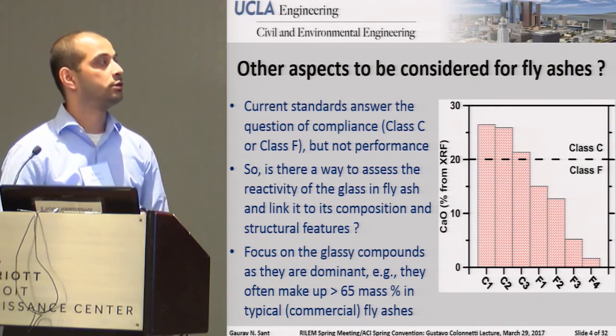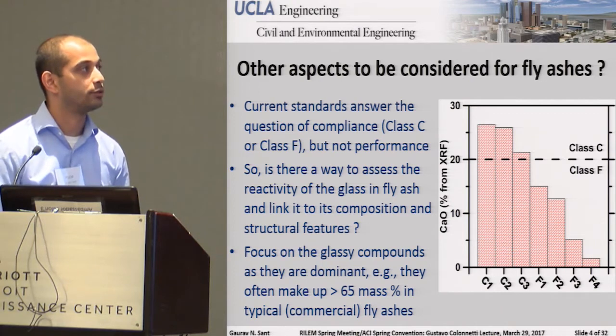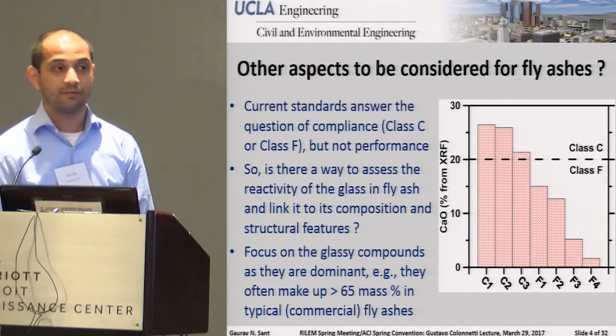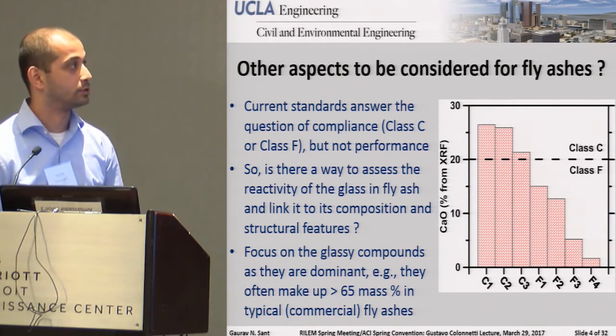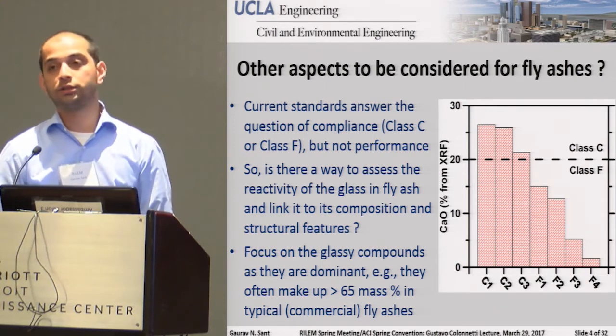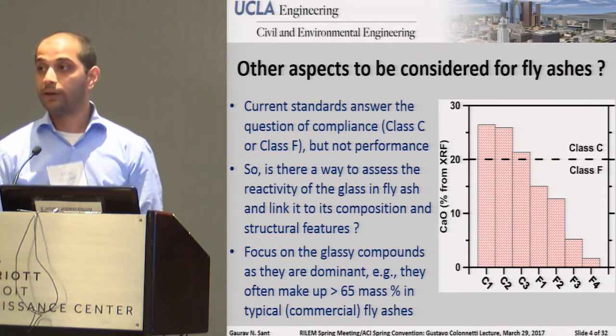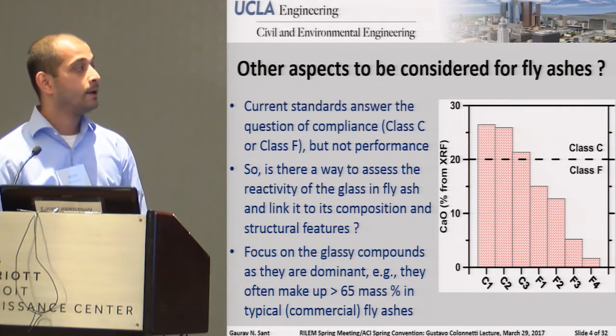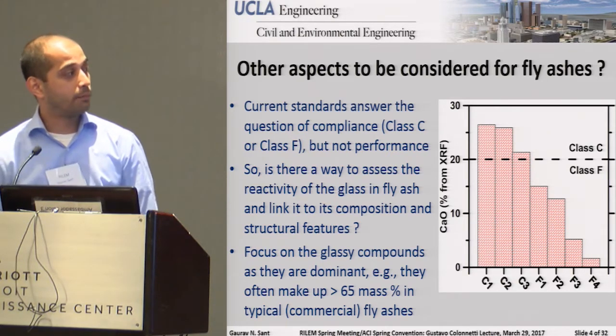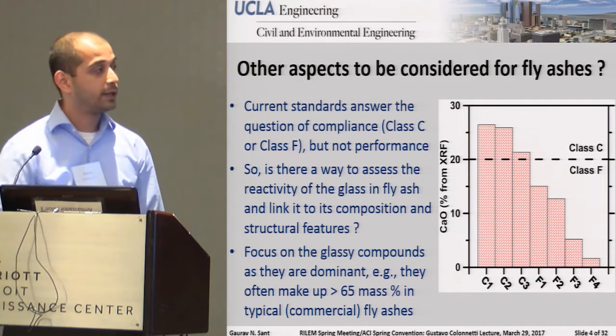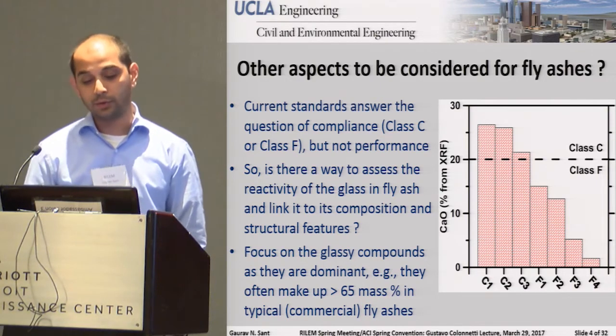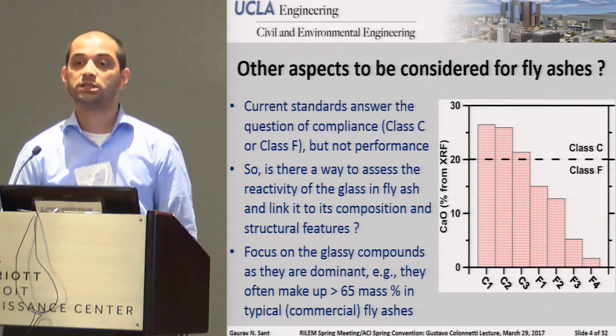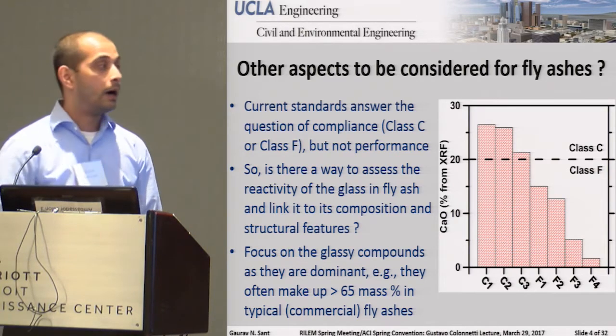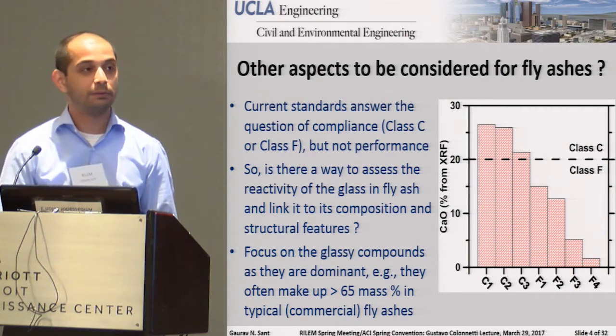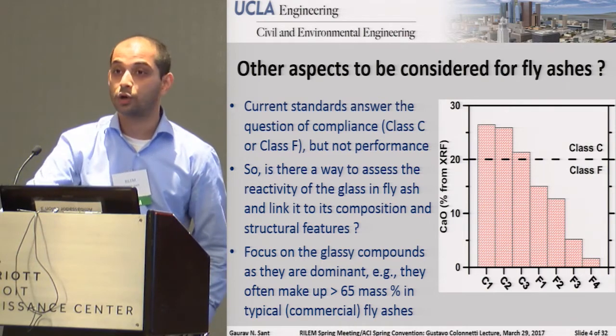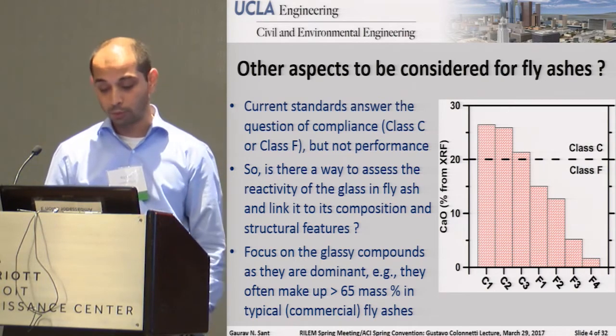So really, I think the first question to lead in with is there a way to assess the reactivity of the glassy components in a fly ash? And I'll tell you why I focus on the glassy components in a little while. And then link its composition and structural features to reactivity, which would be, for example, a surrogate of performance. Of course, we want to focus on the glassy compounds because they are dominant. And I'm going to speak specifically in the context of fly ashes. In general, for everything that we've seen, the glass makes up at least about 65% of the fly ash, if not more. Of course, you'll find the one-off fly ash which has 50% glass, but I think broadly speaking, 65 is about a good number to be looking at. So you want to look at really the dominant component.